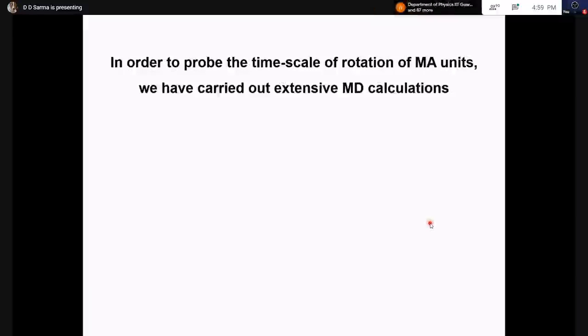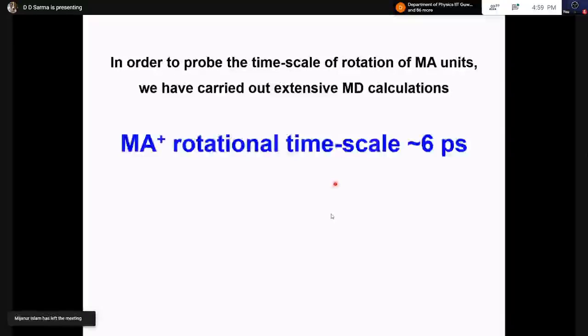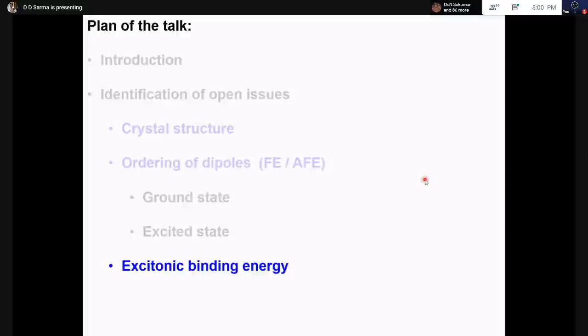And this is where we did extensive MD calculation in collaboration with the Vienna group. And the estimate that we found from there is that it rotates at 6 picoseconds. And no wonder that when you look at it with 1 microsecond, which is like 1 million times slower than 1 picosecond, it looks like freely rotating. So these are rotating at 6 picoseconds, in the order of a few picosecond rotational time scale.